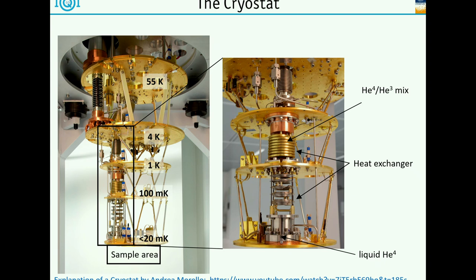Oh, those are gold-plated. These are copper plates, which are gold plated. The gold plating is not there because it has higher heat conductivity. It's there because the copper would oxidize over time, and this layer is a very efficient insulation layer. So whatever I would bolt there wouldn't be thermally connected very well to the plate. If you make that in gold, then it doesn't oxidize, so you can always make good connections.